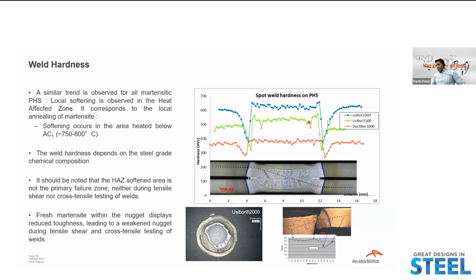But there is a myth. Weld hardness depends on carbon percentage - as you increase your carbon, you're going to have higher hardness. But there is a myth that cross tensile test or shear tensile test fail in the HAZ area or soft zone area. It doesn't actually do that. Actually it fails in the nugget area, as you can see in the picture, where the hardness is really high. Why is it happening? Obviously you have fresh martensite in the nugget zone area, and this fresh martensite actually has low toughness. So when you have low toughness, failure usually occurs in the nugget, right? This is for cross tensile test and shear tensile test cases. So that's the logic behind this one. In industry there's a lot of myth that it's going to fail in the HAZ area, but in reality it will fail in the nugget area.